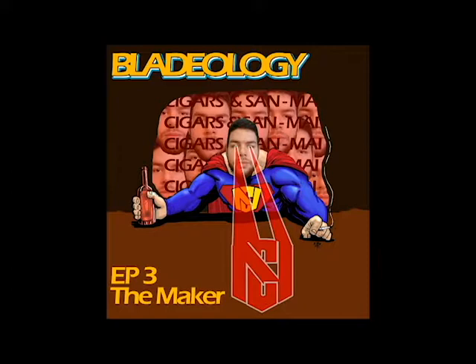Now, if it's not hardened, the titanium lock face is harder than the steel blade. It's going to start mushrooming out and wearing away your steel. On a traditional knife that's done right, it's hardened, the blade is 60 and the titanium is 42. But titanium has beautiful properties, and the reason we use titanium is that it's very springy, it bounces back. Steel doesn't, so you push against it, it's going to stay where it is and deform, so it's going to start mushrooming out. Titanium is going to push away, but once you unlock the knife, it's going to push back. This is something you're never going to see, but on the micro level, that lock face will keep bouncing back.